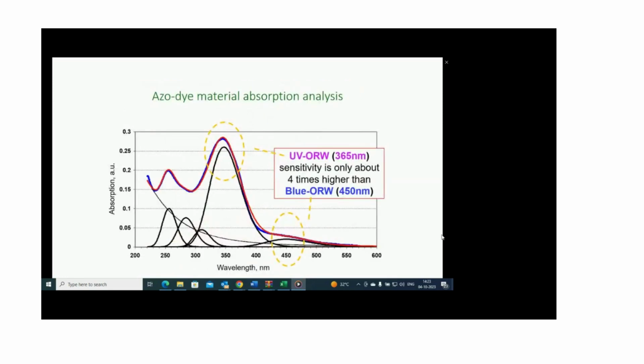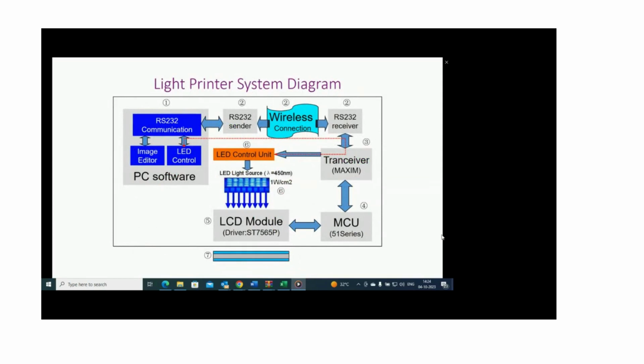You don't need to use UV light. You can use blue LED light of 450 nanometers. So you can make an image on the computer, transfer it by RF to this LCD module, an amplitude modulator, and then shine the light, and you will put the picture on the liquid crystal layer.